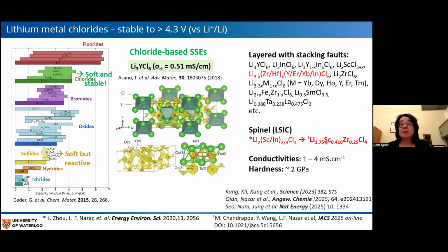So most of these materials, and this has the same conductivity, in fact, as the parent. But the point is that most of these materials have conductivities around 1 to 4 millisiemens per centimeter and hardness values about 2 gigapascals. And as I said, I can't possibly decorate this slide with all of the people that have contributed to this field, but I just wanted to highlight 3 publications which are particularly interesting on these materials down below.